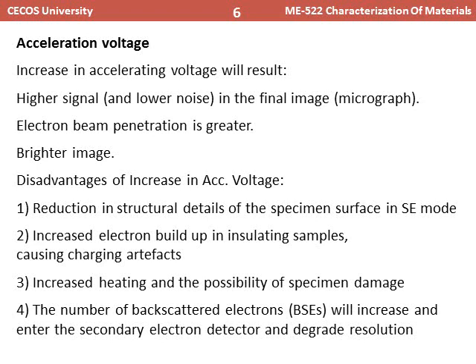Secondly, if we increase the accelerating voltage, then there is increased electron build up in insulating samples. If the electrons build up on the insulating samples, they cause charging, and ultimately this charging will produce artifacts.